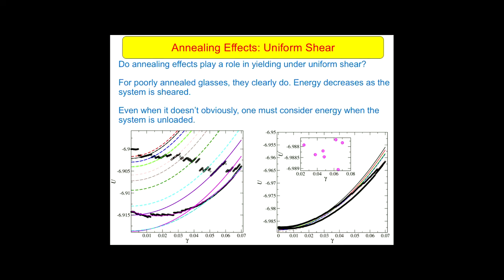Here is the change in energy as a function of the number of cycles. This is just redrawing the data that I already showed, which shows that there is in fact a 1 over n scaling of the energy change from cycle to cycle, which will give you a logarithmic decrease in the energy. And so one can ask, is this only a property of cyclic deformation, or are annealing effects also important when one is looking at uniform shear deformation?